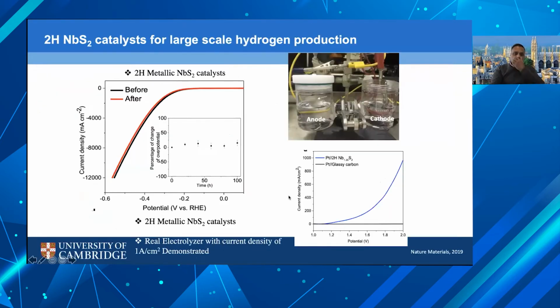So to cut a long story short, we've been working since 2013 to make good MoS2 catalysts. And what we learned is that the best catalysts are those that are very metallic and have good thermodynamics. It turns out that niobium disulfide is the ideal catalyst for HER, because niobium disulfide is highly conducting, and the thermodynamics of niobium for HER are quite good.